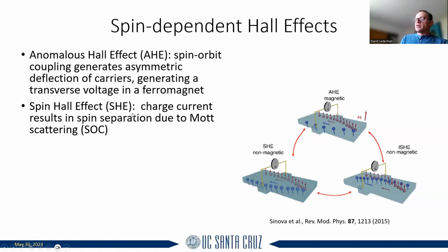Okay. Then related to that is the spin Hall effect, where in this case, let's say the material is not magnetic. What happens is you would get an equal number of spin ups and spin downs on both sides. You would not detect an electrical signal. But if you had some way of detecting this, if you were only sensitive to the spin, you would actually be able to see that. And people have done this experiment, using the magneto-optic Kerr effect, for example, and you can actually see the spin Hall effect.